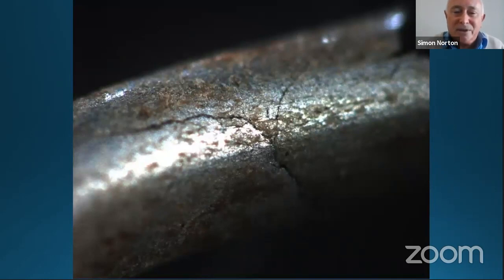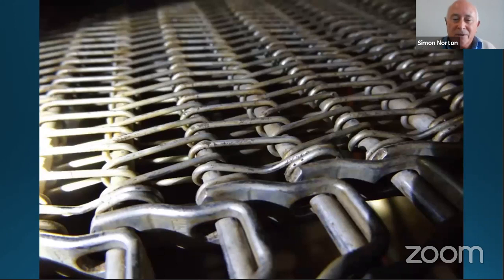And we realized then that what was happening was the wires were obviously under tension from the formation of the wire, so there's residual stress. The temperature in the dryer was 82 degrees centigrade, so there's a high temperature. There were chlorides used to drench the sausages, and you've got the combination sufficient for stress corrosion cracking of 304. This was 304 stainless steel, and the other side fittings that I showed you here were 316. So what they needed to do was go to the supplier and say, look, we'd like a duplex stainless steel belt so that we can actually resist stress corrosion cracking.